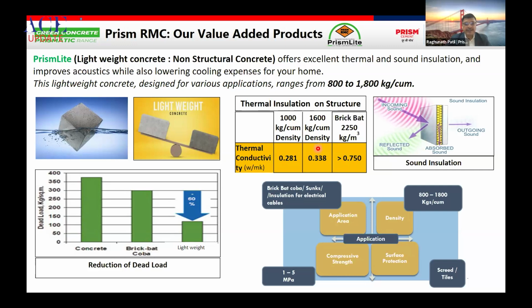Actually, for the last or terrace slab, waterproofing is generally done, and to cover the waterproofing, the brick bat coba layer is generally put over it. This brick bat coba generally takes around 10 to 15 days to make around 40 to 50 cubic meters of concrete. This lightweight concrete we can put in one day by using the pump, and as compared to brick bat coba, the thermal conductivity is very low.